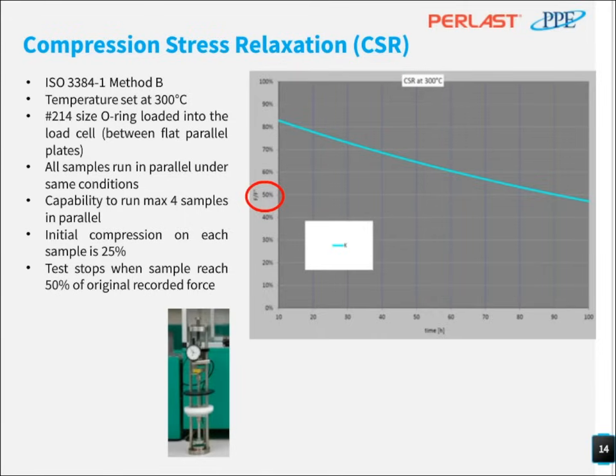The graph you can see on the right gives the information about the actual force by the initial force, and you can see a decay in the sealing force against the initial force over a period of time. According to the ISO standards, this test finishes when the actual force reaches 50% of the initial force. However, considering that the semiconductor applications are mostly under vacuum, even 20% remaining force will be enough to hold the vacuum. Let's now see the actual graph in the next slide.